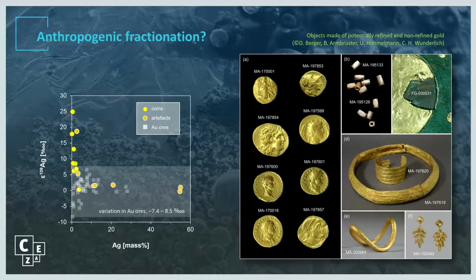And what we did in the next step, we analyzed a couple of gold objects from different time periods. What you see here in this diagram is that there are a couple of objects, especially gold coins, that possess silver isotope compositions that lie outside the natural variation. This is a clear indication for the use of the cementation process for purifying this gold, and this is the first time that we have a tool for recognizing this process.